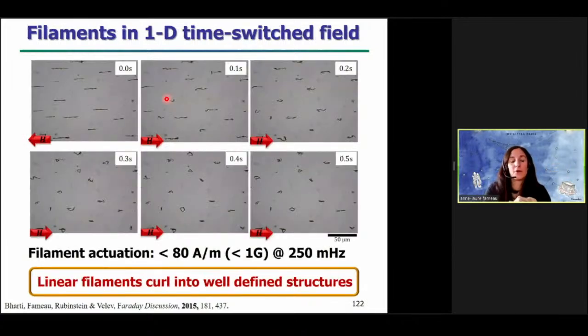Then we studied the properties of these filaments in a one-dimension time switch field. So here you can see that we first produce filaments along the direction of the applied magnetic field. And in the second picture, I just changed the direction of the applied magnetic field like this. And you can see that automatically all the filaments just bend and try to follow the change of field polarization. And you can see that they all bend and form at the end self-closed structures. So all the linear filaments turn into well-defined structures, and this self-closed structure remains even after switching off the magnetic field.